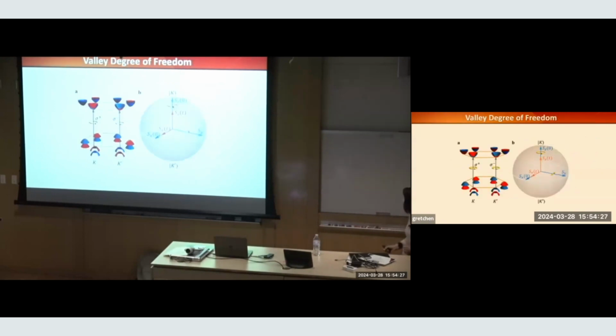Another thing that's somewhat different is this exciton resonance that I show you, this peak. In gallium arsenide, good old gallium arsenide, that happened in the center of the Brillouin zone. But in this material, these transitions happen at the boundary of the Brillouin zone. This is the hexagonal Brillouin zone, and these transitions for the excitons happen at two valleys, K and K prime valley. They are inequivalent. They're related to each other by what we like to say time reversal symmetry.